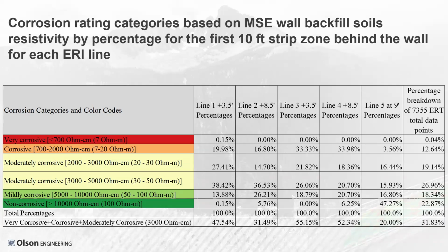So we focused on the first 10 feet, whether it was from the top of the wall next to the pavement in the grassy area that we were able to do the resistivity values along the length of the wall, nominally 850 feet. Then you're looking at the different lines, 1 and 3 are at 3.5 feet, 2 and 4 at 8.5 feet. And line 5 is the top of the MSE wall area, basically the backfill soils, right next to the pavement, about 9 feet behind the wall. So that was a grassy area that was very convenient to spike in the electrodes.